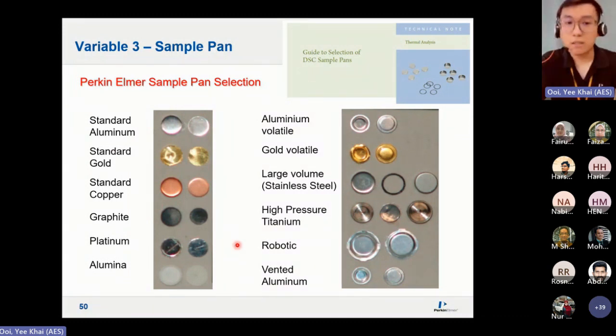Okay, so for anybody running metallic samples, organometallics, or even soldering materials, alloys for example, do not use aluminum, okay, because the metal sample is going to react with your metal pan, forming a new type of alloy, reducing the melting point, and then fusing together with your furnace. Hence, an alumina pan is recommended. So in DSC you also have alumina. Alumina means ceramics or aluminum oxide basically, okay?